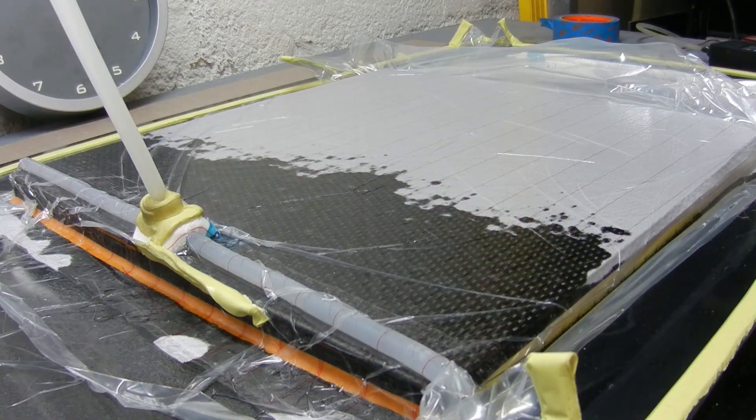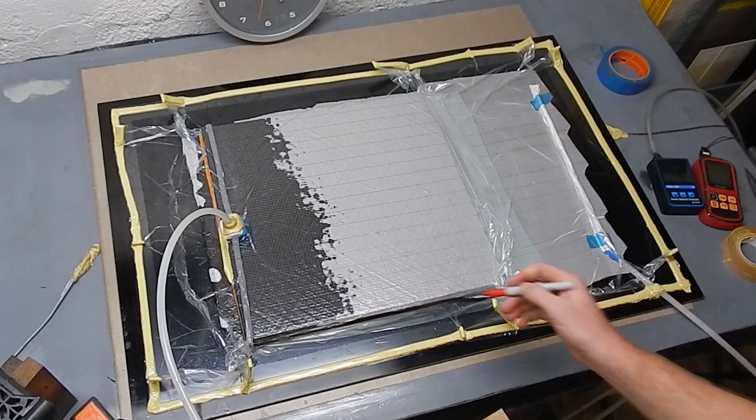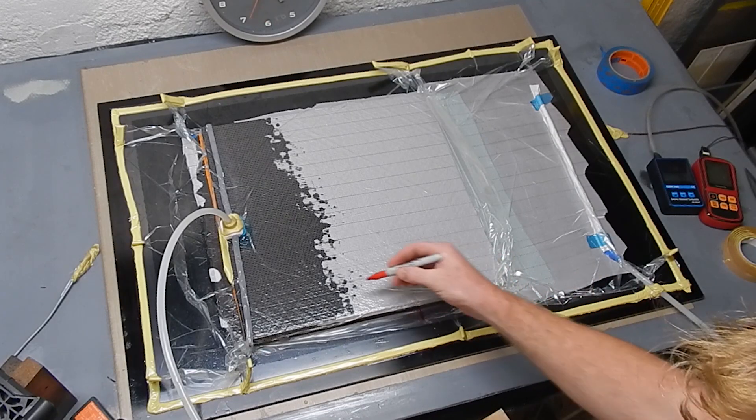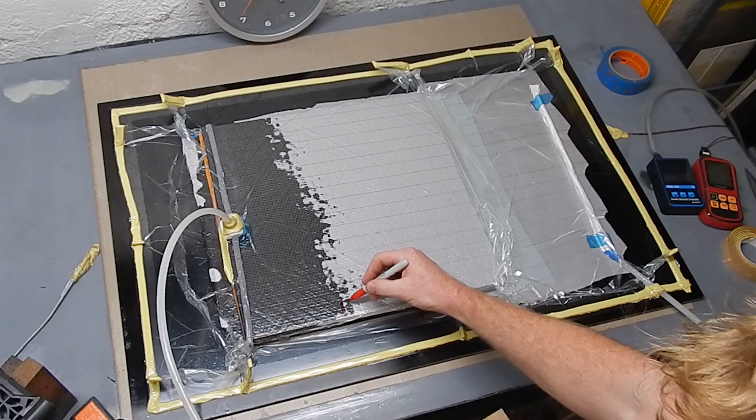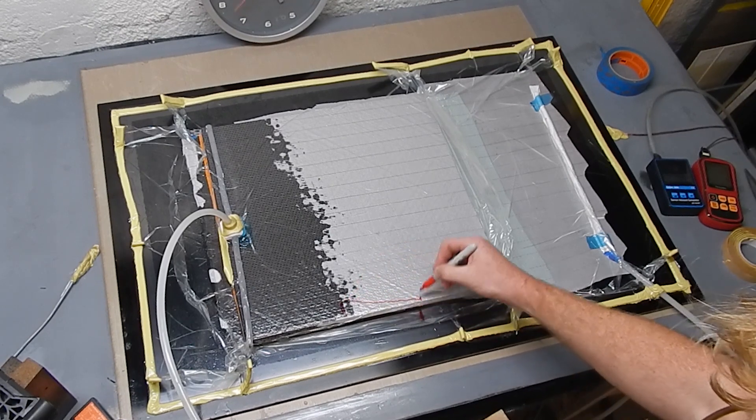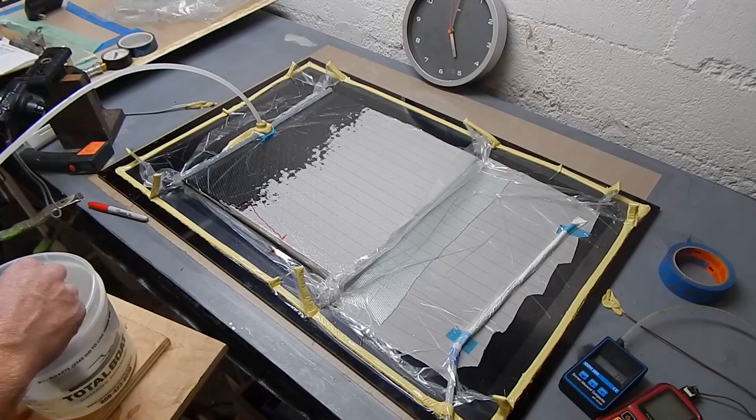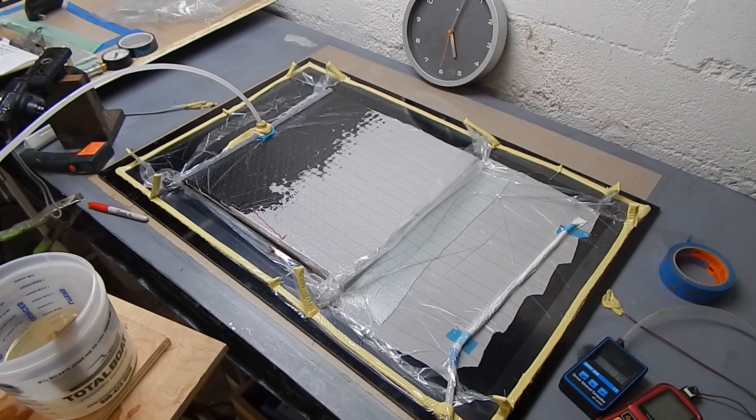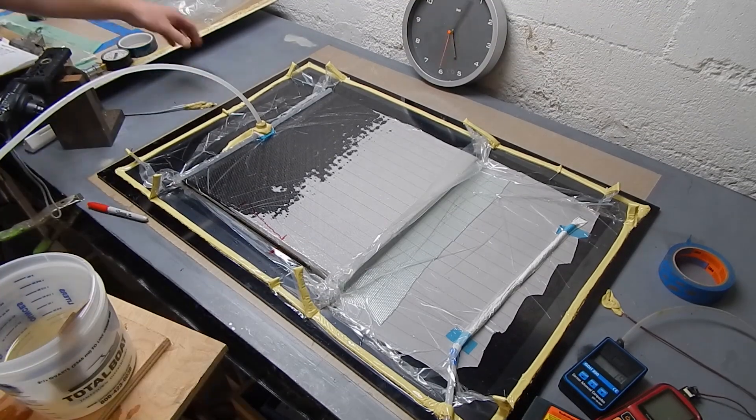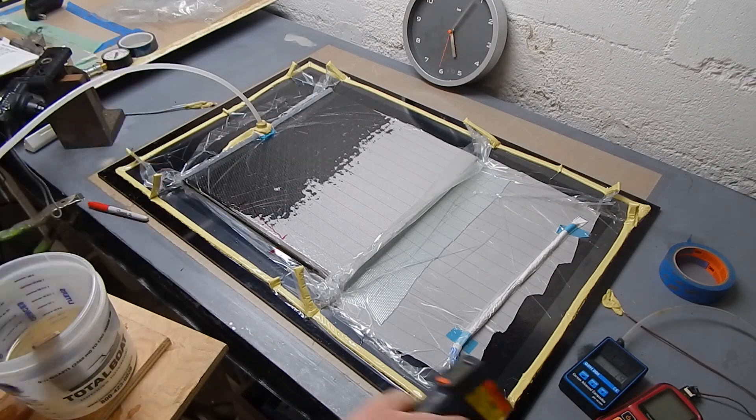So filling here, I can see that's the distance between the flow on the bottom, which is way ahead where the red mark is, and the one on the surface. I think this is because the table is warm, and it's warmer on the bottom. Resin is feeding through, and it's moving faster along the bottom surface.